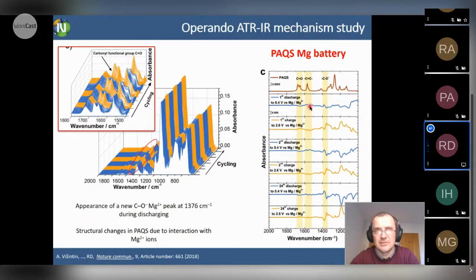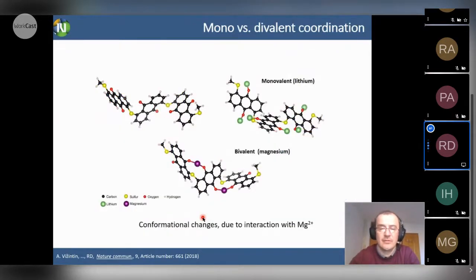This can also be done by subtraction of IR spectra from the beginning and at the end. And this is only the first attempt that we were able to see the activity of these quinone groups. But nowadays we can also monitor the formation of radicals. We can monitor some irreversible changes in the organic molecules and so on. The major part was the difference that we found between interacting this quinone moiety with lithium, or with magnesium, because this quinonyl group was found at a different position. There was only a 5 inverse centimeter difference, but already this 5 inverse centimeter difference gave a suggestion that there should be something different with the conformation of the anthraquinone groups.